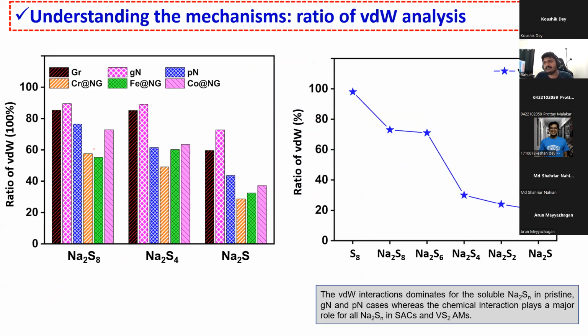The first analysis we did was the ratio of van der Waals analysis. If the van der Waals interaction is higher, then the chemical interaction will be lower, and there won't be much interaction between them. First we talked about the carbon-based material. You can see that for the carbon-based material, the ratio of van der Waals interaction is very high. That indicates that there is only a van der Waals interaction between the carbon and the polysulfide, and because of that the interaction energy is weaker.